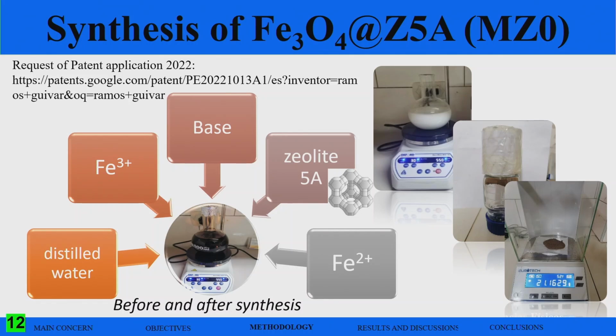People know that. Basically, the zeolites have this structure. It's a cage structure, and the porosity will be very selective depending on the molecule you want to adsorb. You can adsorb water, hydrogen, and other molecules like heavy metals, of course, but it will depend on the ring size of this zeolite. Why I use zeolite and in which proportions, I cannot mention a lot about the procedure because it's under a patent application this year, but I can mention the procedure to follow to prepare magnetic nanohybrids of iron oxide nanoparticles and zeolite.